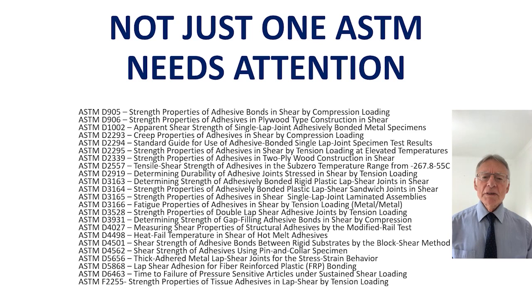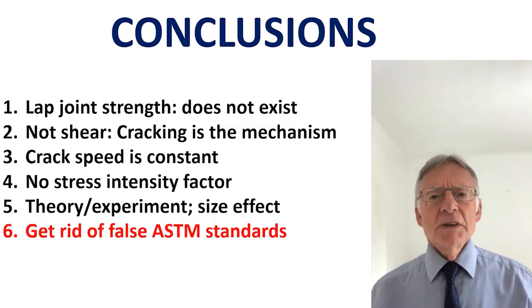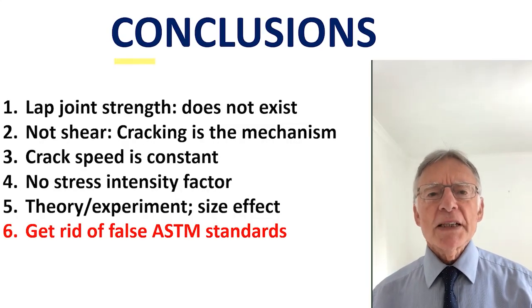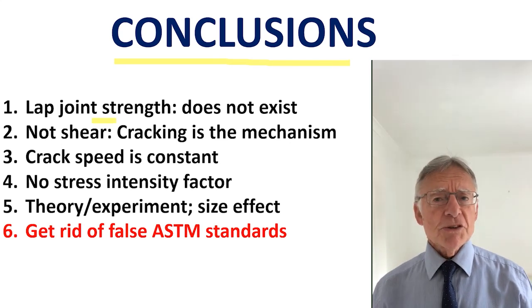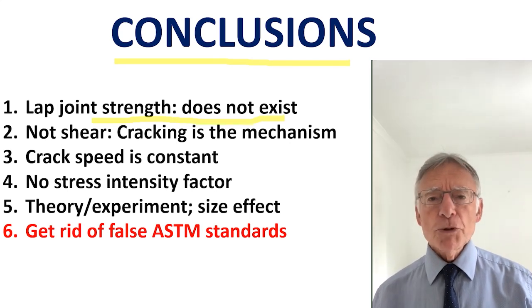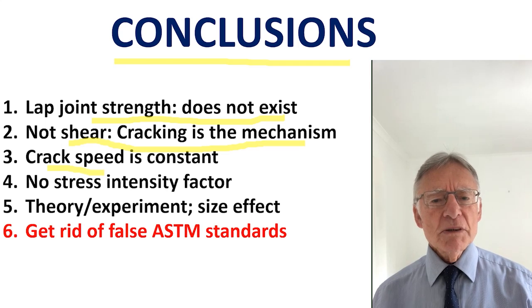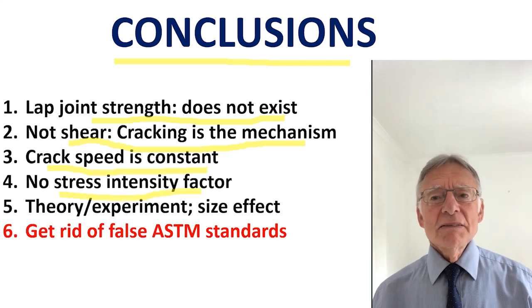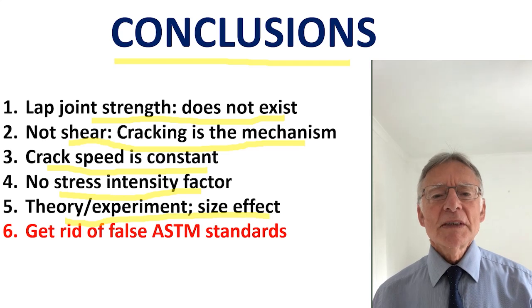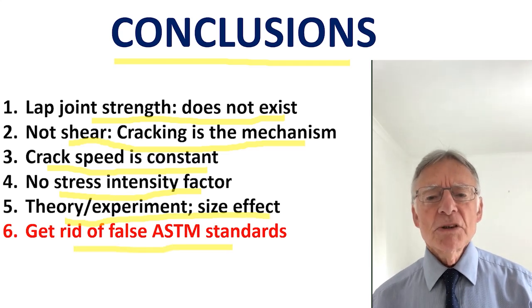It is not just one ASTM standard that causes problems. All these ASTM documents talk about strength and shear. They're wrong. The description of the test as a shear strength test is not correct. The important parameter when it cracks is toughness. We need to correct these errors in fracture mechanics. Lap joint strength does not exist because the fracture force is not proportional to the area. It's not shear, it's cracking. The crack speed is constant, there's no stress intensity factor. The strength depends on sample size. Let's correct these errors today.